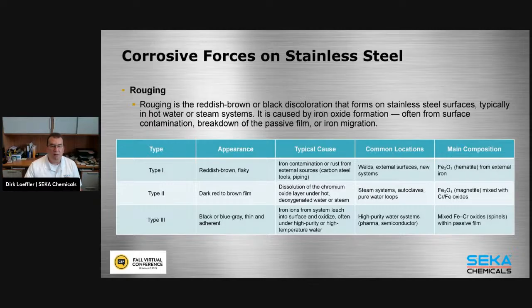Type 1 is generally something that happens somewhere else and just gets transported into your system. That's generally the one that can be easily fixed. It usually looks reddish brown, flaky. It's generally an iron contamination or rust from an external source, carbon steel and piping or something. And it can generally be removed fairly easily with a strong acid, CIP, or a repassivation cycle type of thing. Nitric acid, citric acid can take it off.